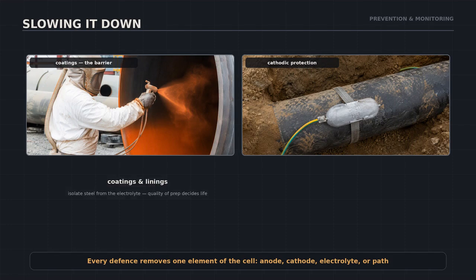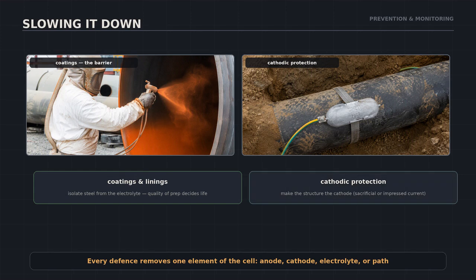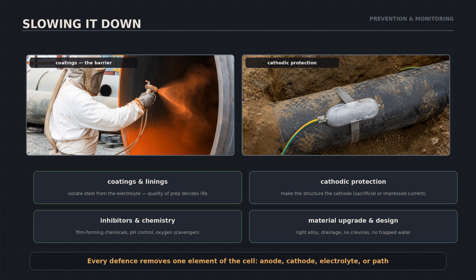Prevention removes one element of the cell. Coatings and linings isolate the steel from the electrolyte, and surface preparation decides their life. Cathodic protection makes the structure the cathode, with sacrificial anodes or impressed current, so it cannot dissolve. Inhibitors and chemistry control build a protective film from the inside: filming amines, oxygen scavengers, pH control. And good design avoids the traps: the right alloy, full drainage, no crevices, no dead legs, no trapped water. Every defense is the same idea: break the cell.